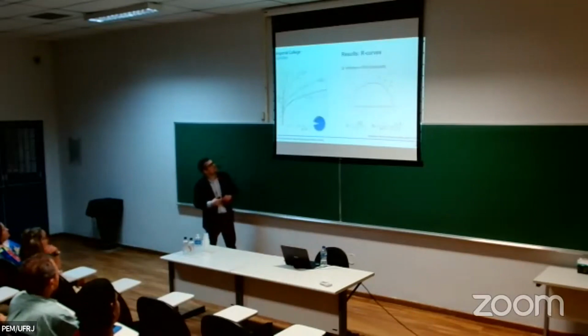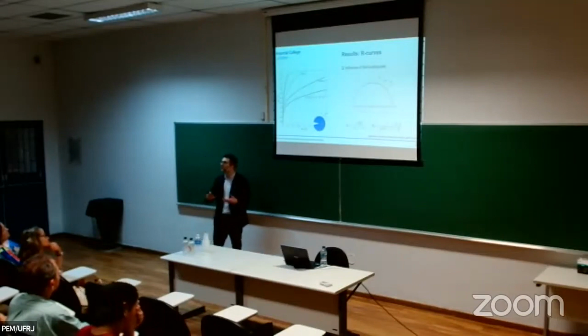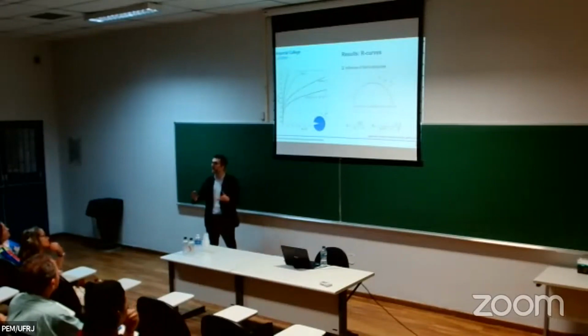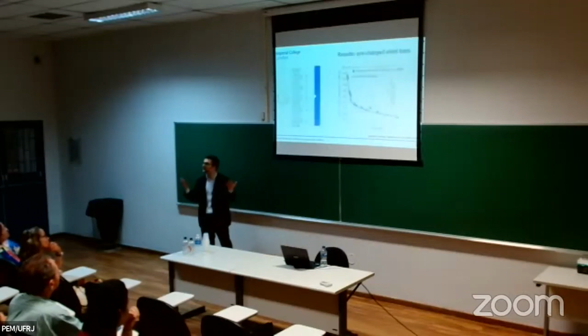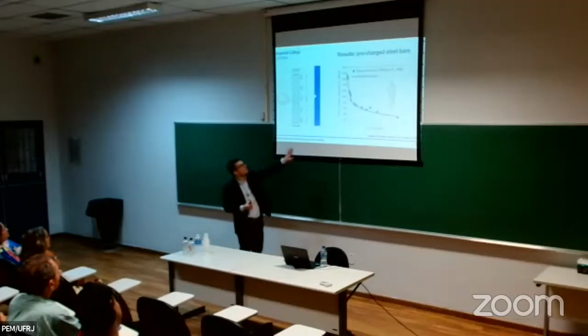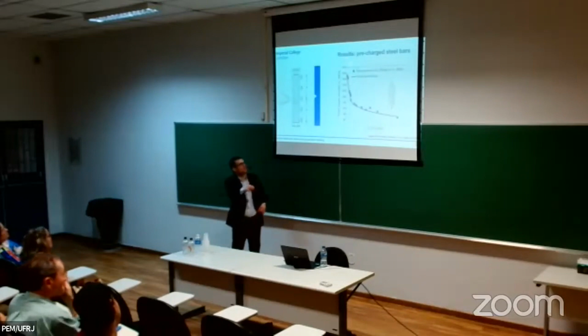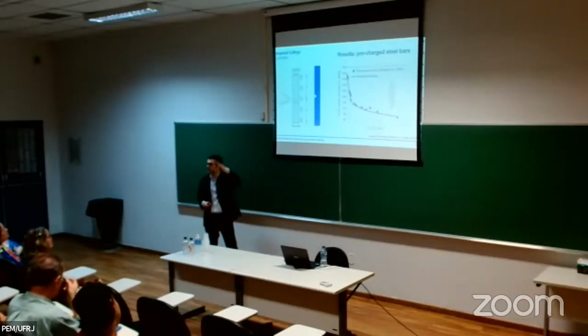Here you see results for different loading rates. And again, we see another effect that we see in experiments. If you load your sample very slowly, you allow more time for the hydrogen to accumulate in the fracture region, and therefore you lower your fracture resistance. But we can also provide quantitative agreement with experiments. Here you see experiments in pre-charged steel bars. These are measures of notch tensile strength versus hydrogen concentration, and you can see that the model agrees very well with the experiment, those symbols that we see there.